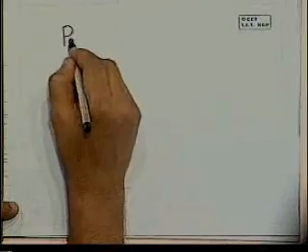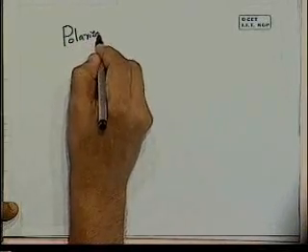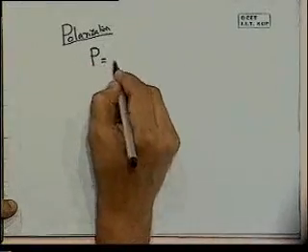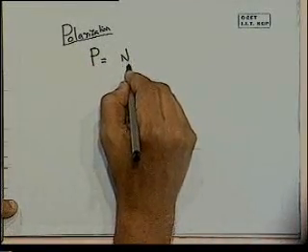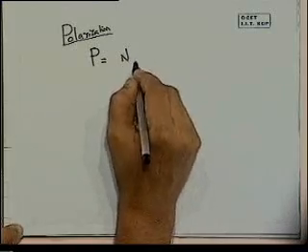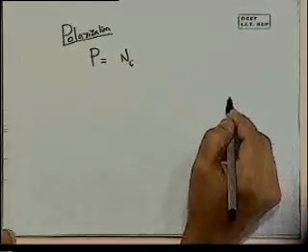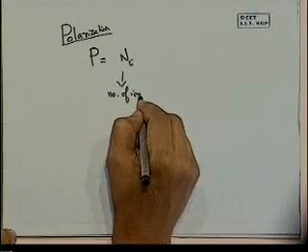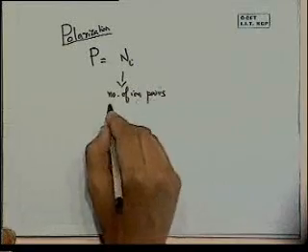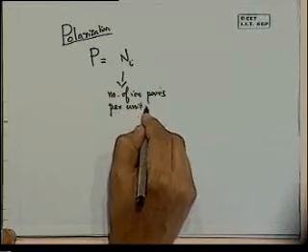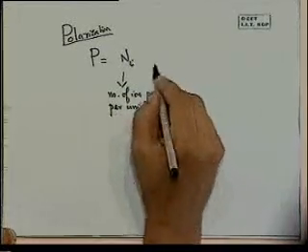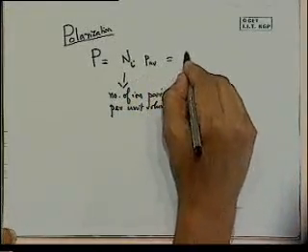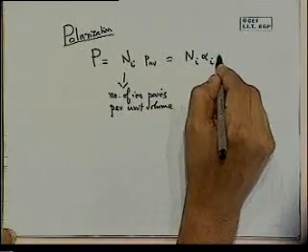When we consider it in terms of polarization, we can write then that P, as before, the polarization is equal to N, where we are not talking of the molecules now, but the number of ion pairs per unit volume, times the average dipole moment, which we now express as Ni alpha i.